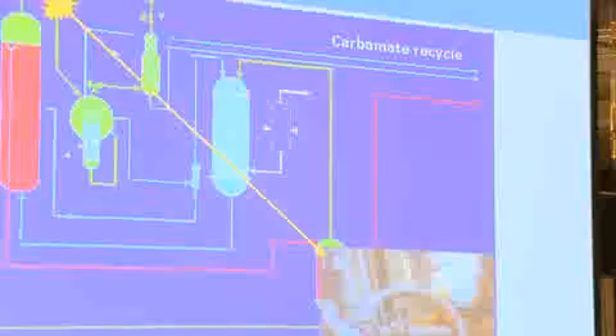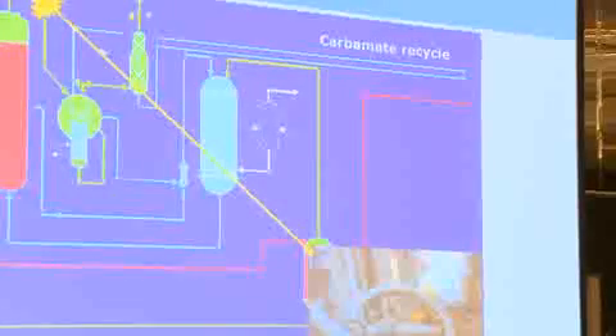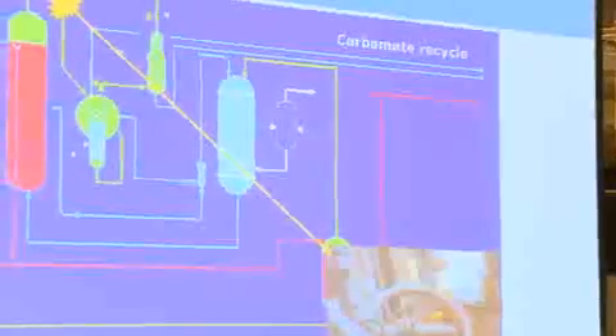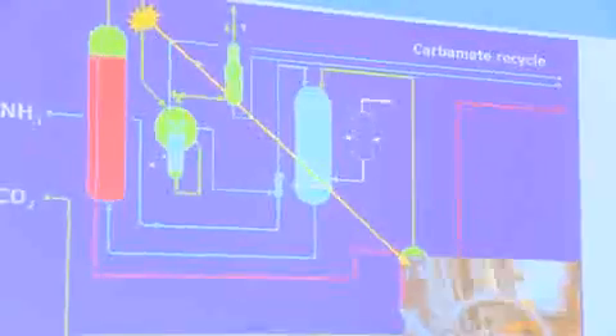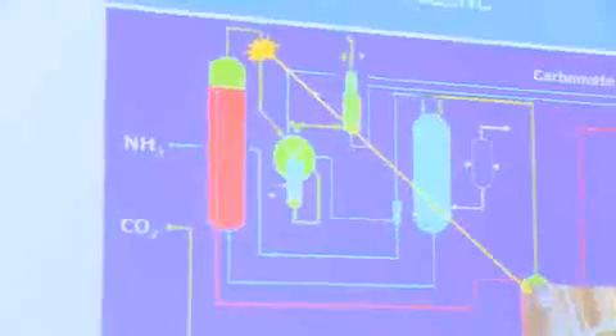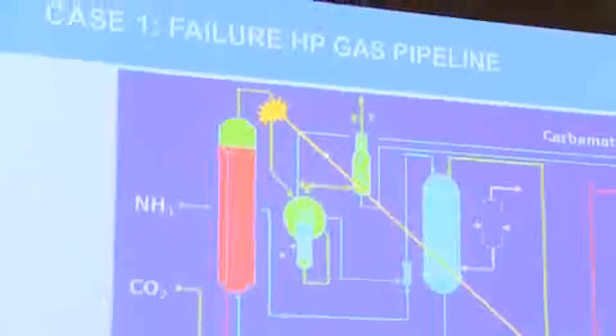In this case, the failure occurred in the line that runs from the top of the reactor to the scrubber. We learned from the plant that before this rupture occurred, they had upset conditions at several locations. During this upset, a hard white crystalline substance was deposited in the equipment and also in the pipeline. After each event, they would clean the equipment and the pipeline with steam condensate and then inspect the equipment, but the pipeline was not further investigated. Unfortunately, the pipe ruptured, but on the fortunate side, there were no injuries or fatalities.